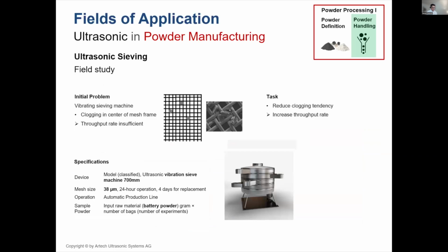Let's have a look at the field study. This study was conducted by our Japanese colleague. As you can see, the problem was, as I outlined before, always the same. It was plugging. The sieve was plugging. The customer used this 700 millimeter diameter sieving machine, so not too big. The mesh opening was 38 microns, and the task was to reduce the clogging tendency and increase the throughput rate. So let's have a look at the results.